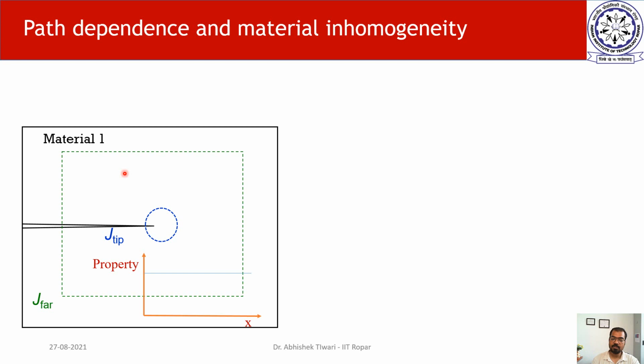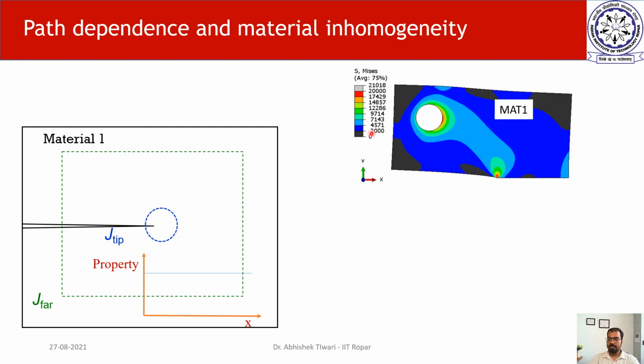So inside the contour there is only one source or sink of energy, in this case is the crack tip, and therefore as long as the contour encompasses only one singularity, I will always get the same value, and that can be seen from the stress distribution of a homogeneous material which looks like this.